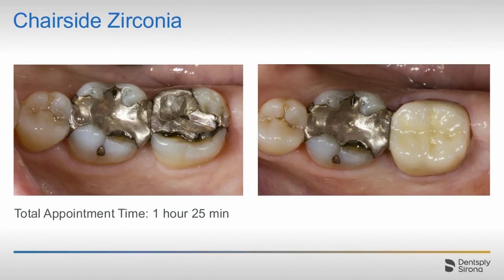Now this looks as if it's stained and glazed, but there was a little infiltration added. Now that's a topic for a separate day, but what infiltration means is I just added a little bit of color in that pre-sintered state, and it's kind of like dyeing an Easter egg. When you add that color to the pre-sintered or white zirconia and you put it in the sintering furnace, it will bake right in, just like dyeing an Easter egg, and then I can hand polish the restoration and you can get this result.